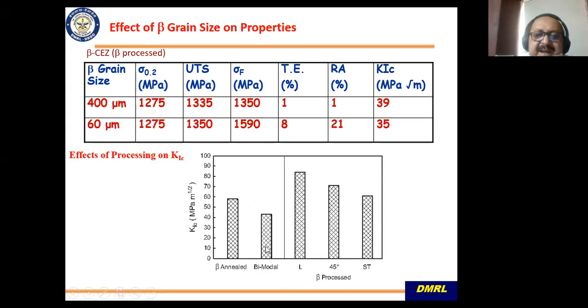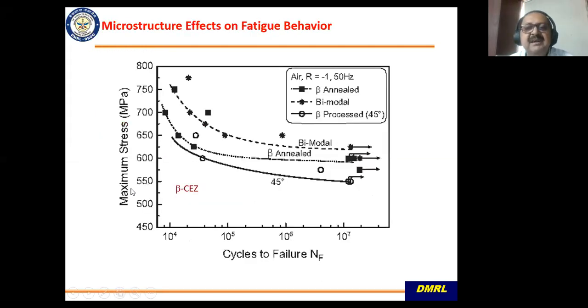And again, a bimodal structure has got a lower fracture toughness as compared to a beta anneal structure, which I have already told. But this is what is being shown here in another alloy, beta CEZ alloy. Again, the effect on fatigue properties, you can see a bimodal microstructure gives a much better fatigue as compared to beta anneal structure. That is why you go for a bimodal structure wherever you have fatigue kind of applications.